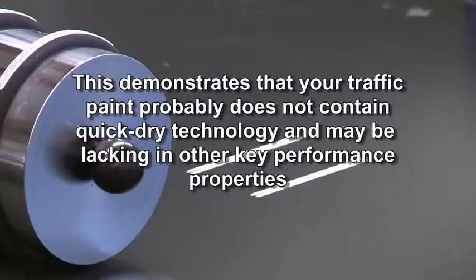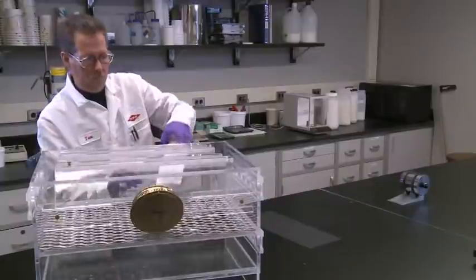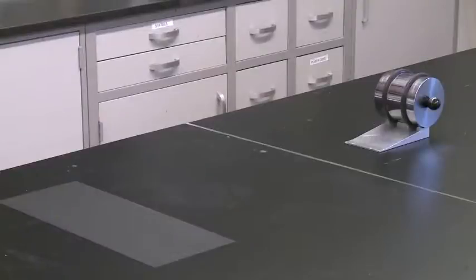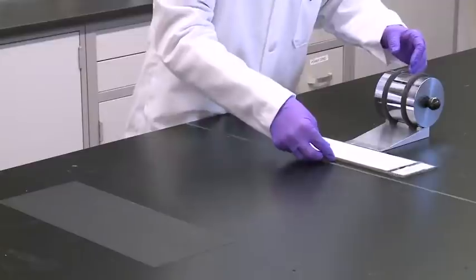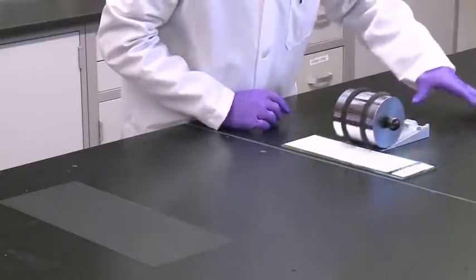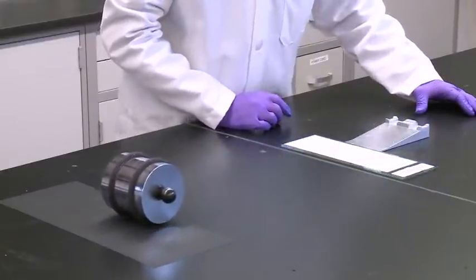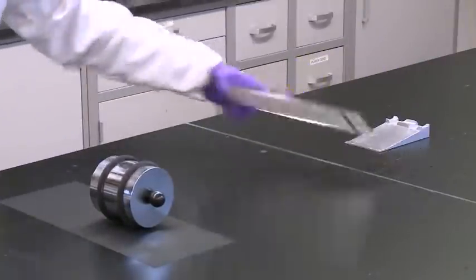After reaching the prescribed exposure time for your pass control sample, remove the glass panel and repeat the process. Place the glass plate against the ramp and release the wheel so that it freely rolls down the ramp, across the paint film, and onto the black paper substrate. Here we see that our pass control paint, made with FASTRACK HE5030 polymer, has no paint marks on the black substrate. This is considered a pass. It shows that you are getting a quick drying paint with performance properties that are needed to produce a bright, visible, and lasting stripe on the road.